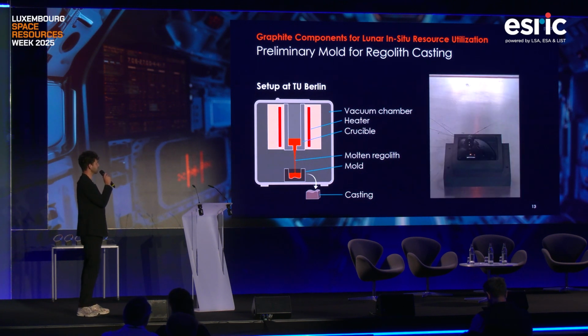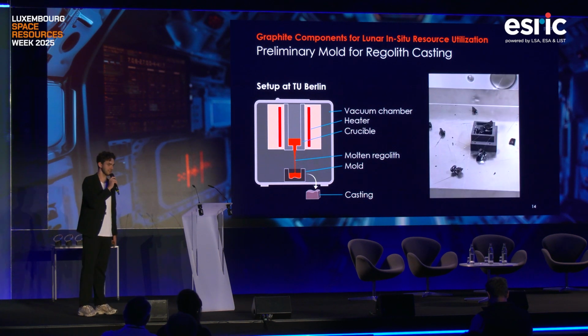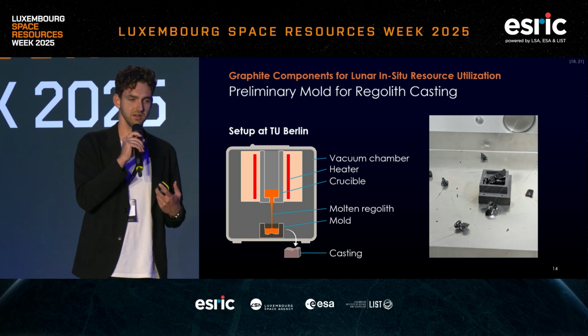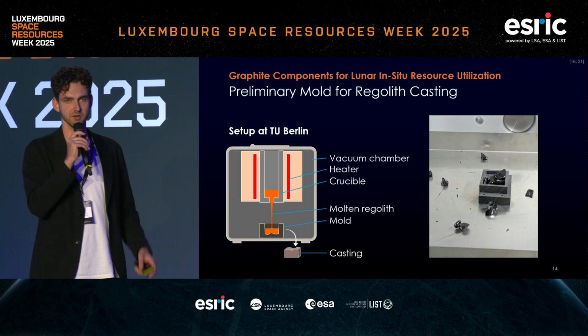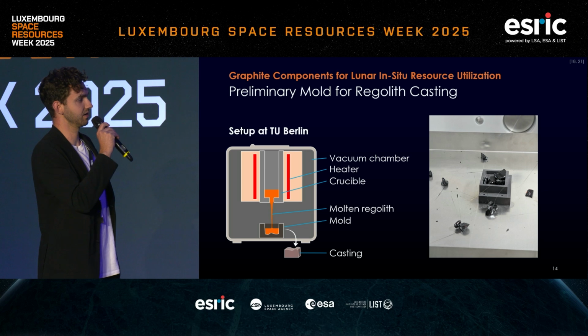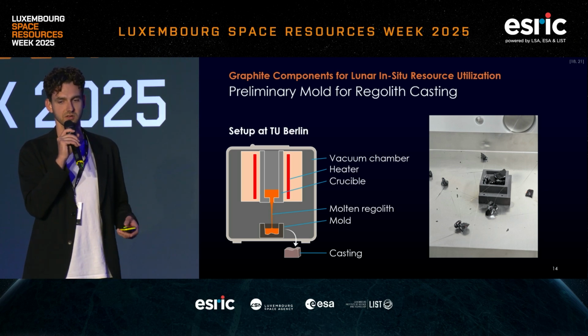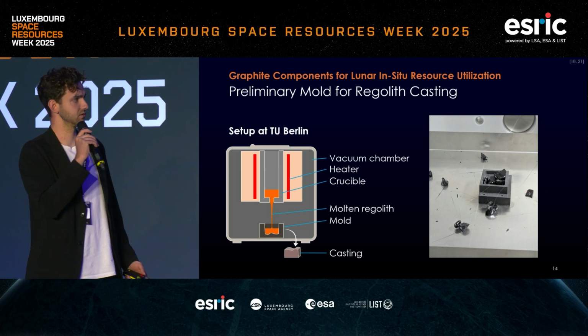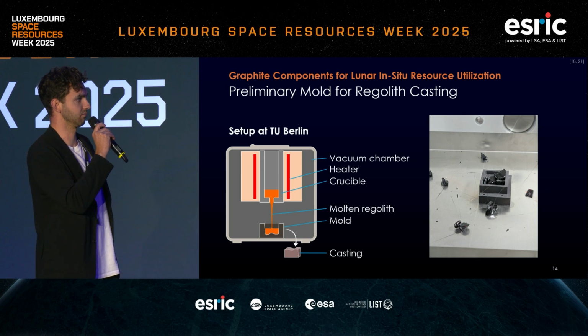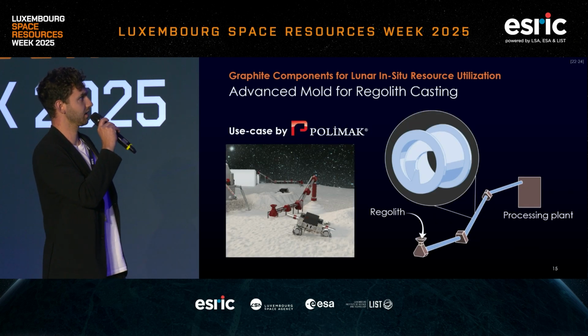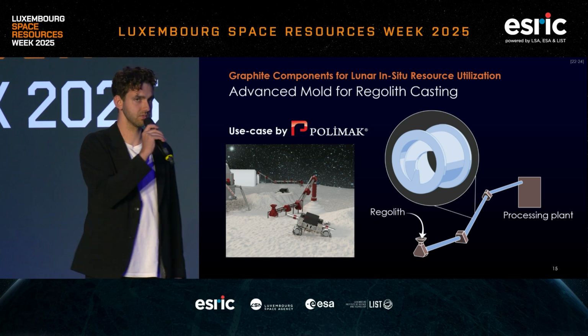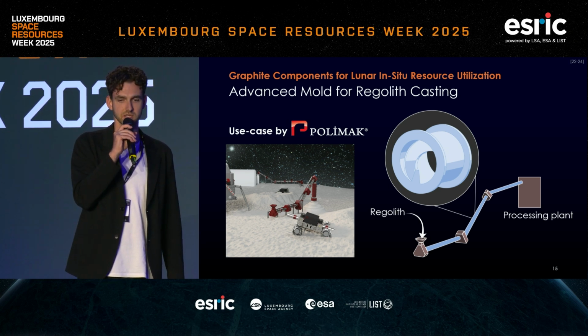Let's zoom into that. Just after the extrusion, you can see the material as it solidifies, but then, surprisingly, the glass didn't survive the thermal tensions and basically exploded into the vacuum chamber. So the lesson learned is that we have to do some sort of annealing in the future to also heat up the mold itself. And this is exactly what we are planning to do with the advanced mold for regolith casting for a use case by POLİMAK.